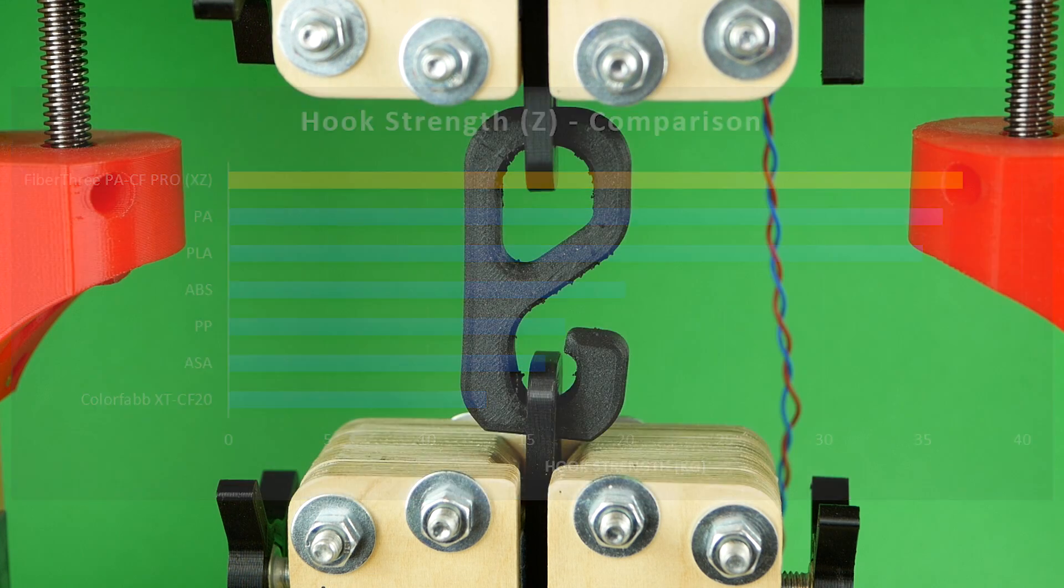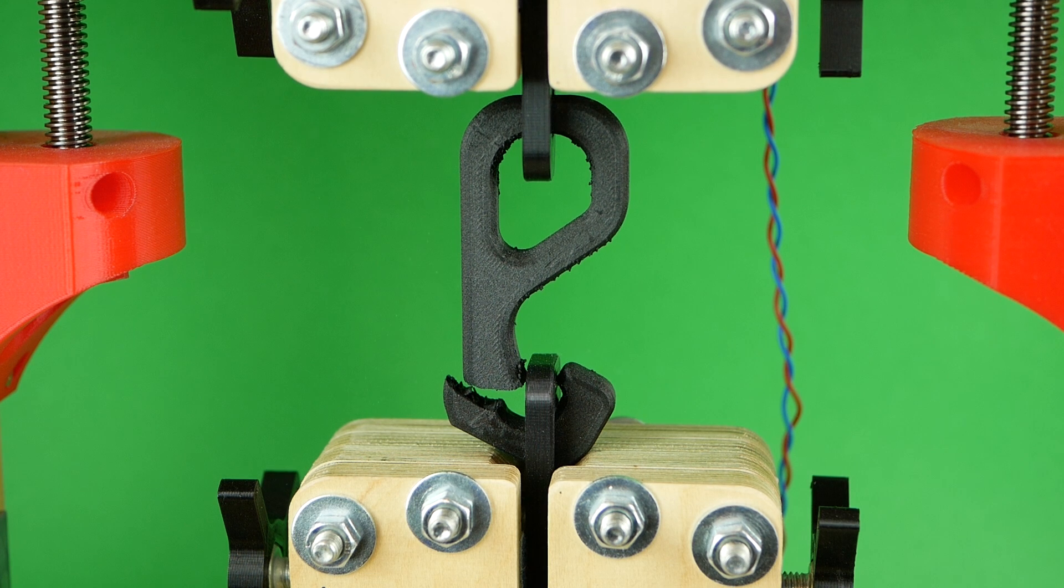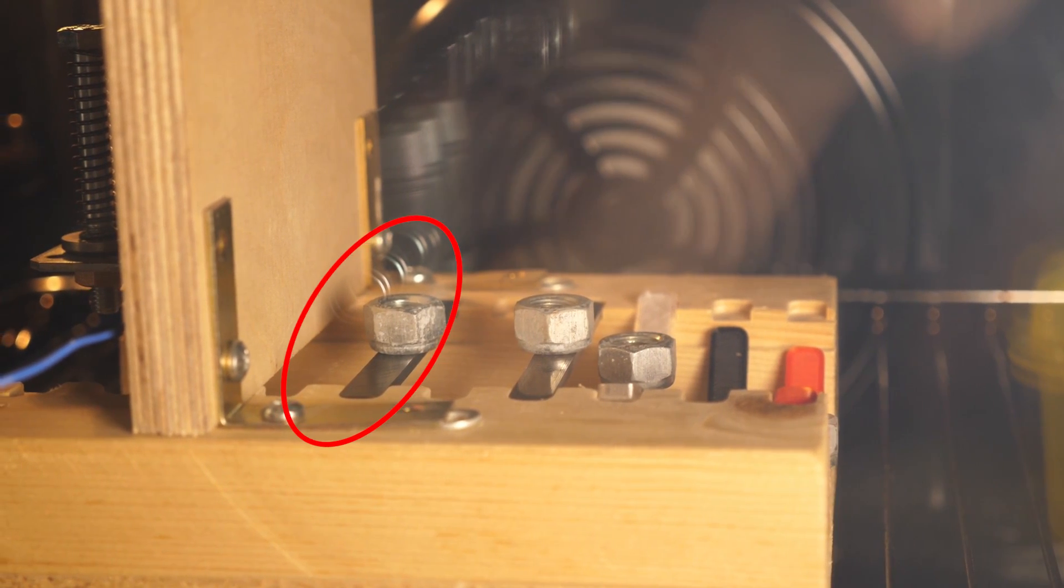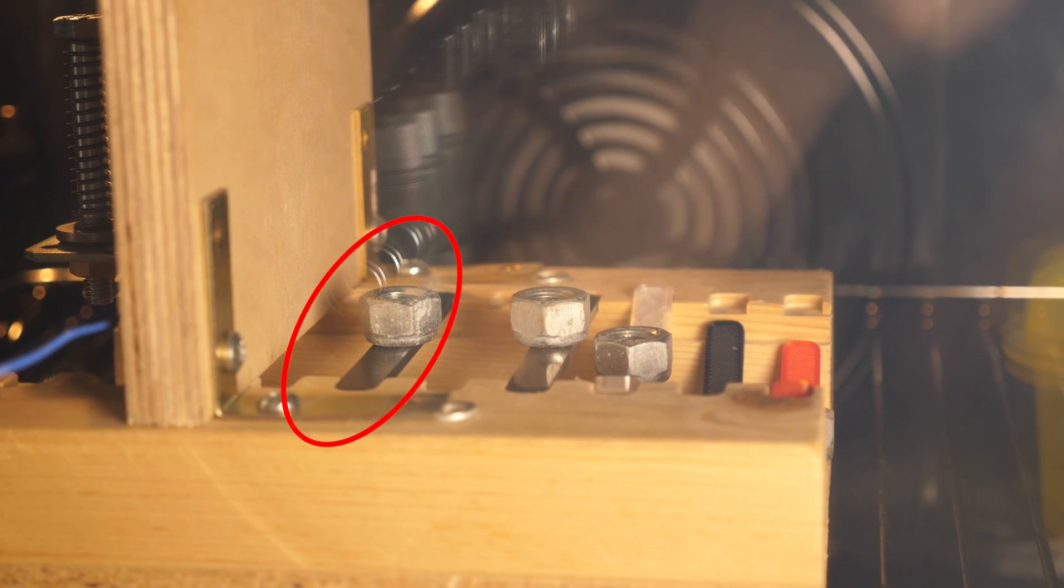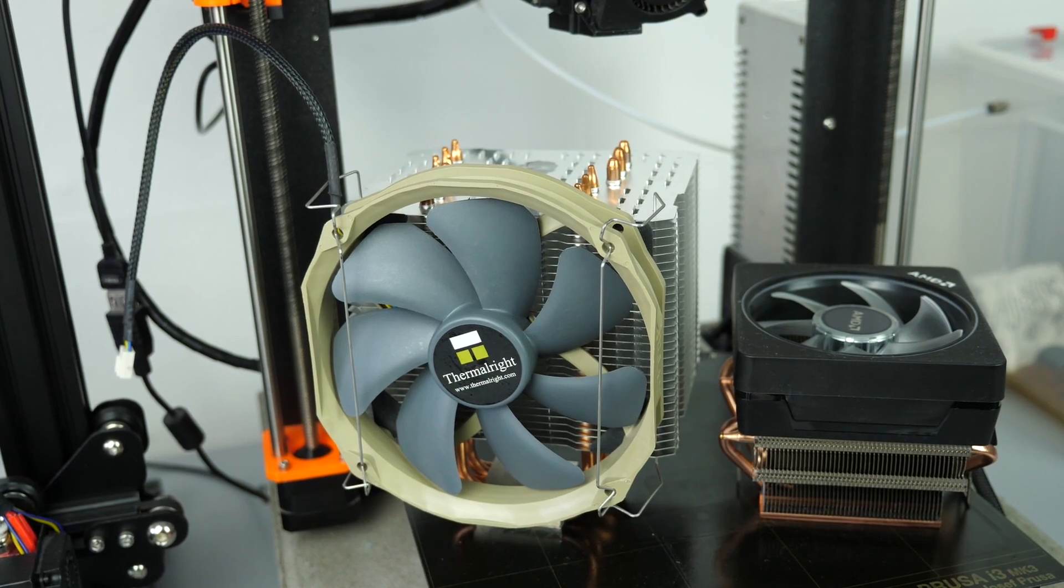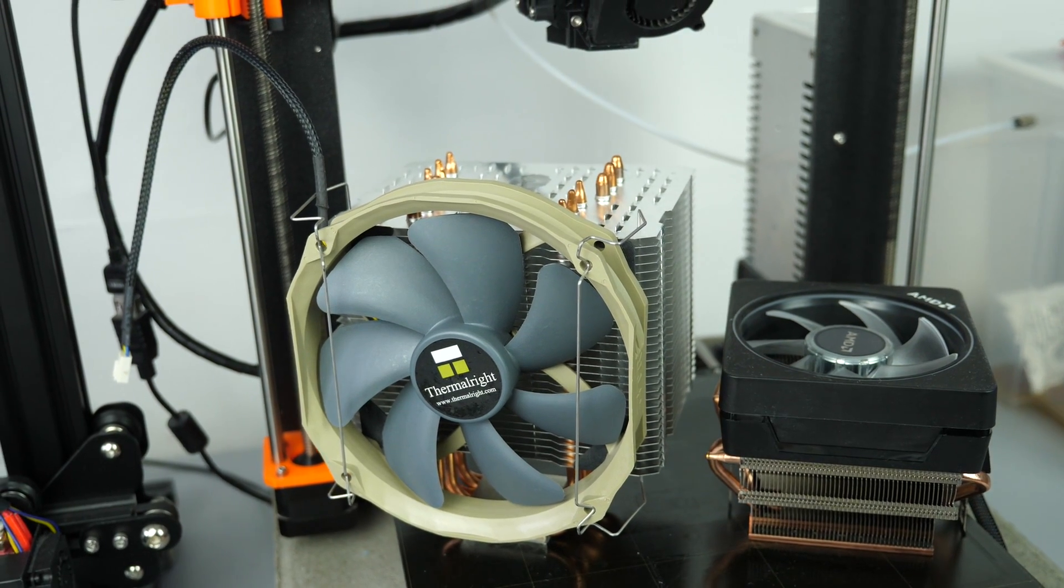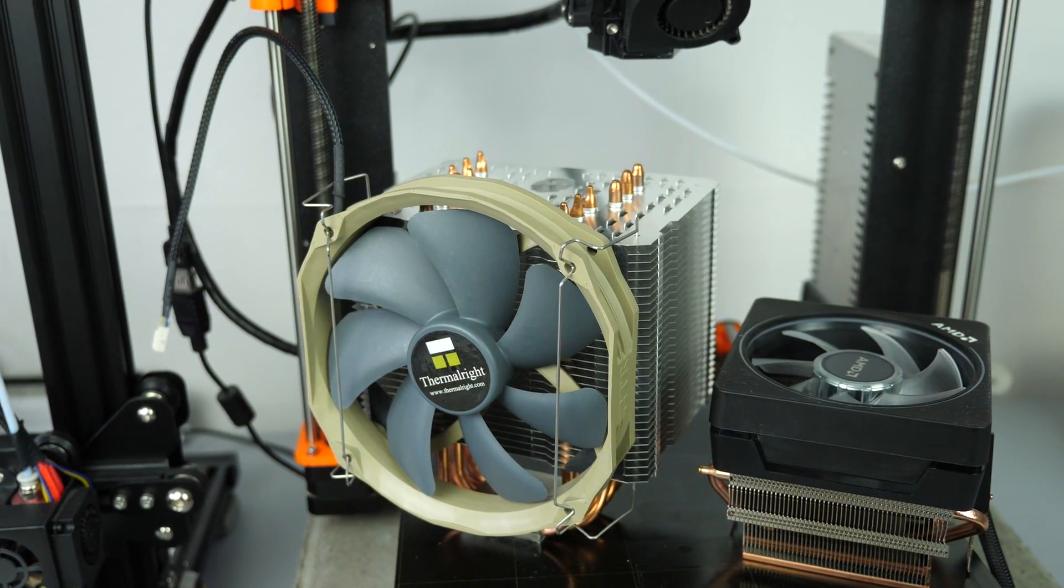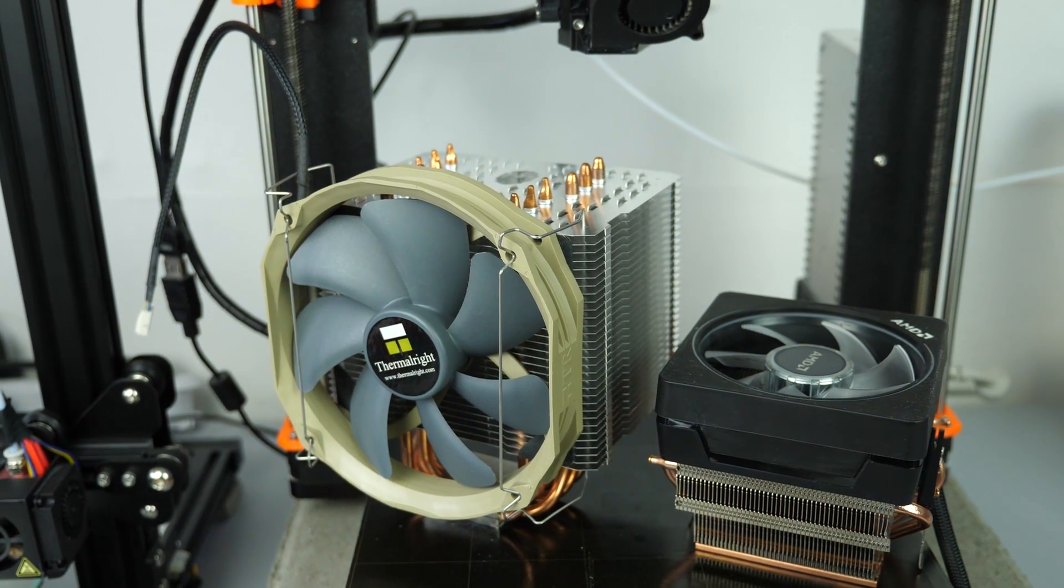I also sneaked the test sample in one of my temperature tests where it didn't fail at over 140 degrees Celsius. Therefore, I thought this would be the perfect material for this application. The CPU cooler bracket doesn't only need to be strong, it also needs to be stiff and capable of handling the temperatures next to the CPU.